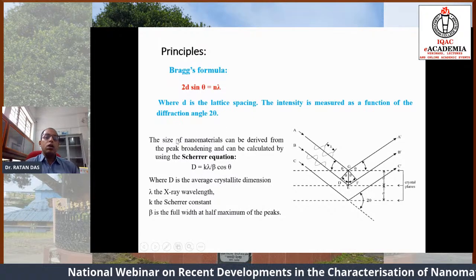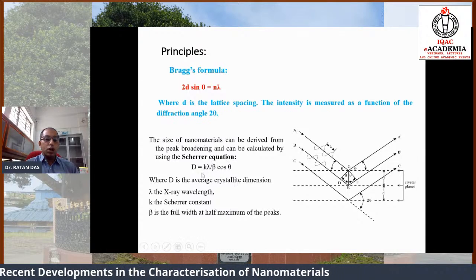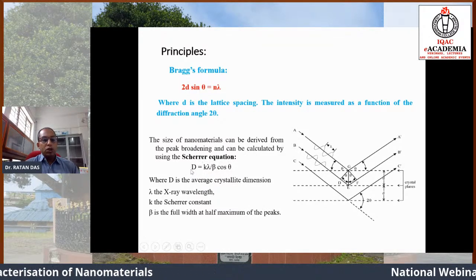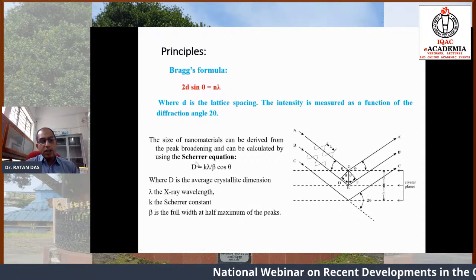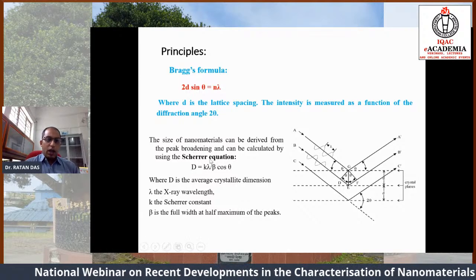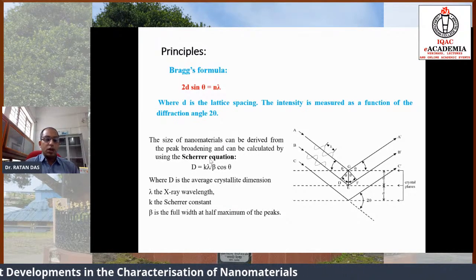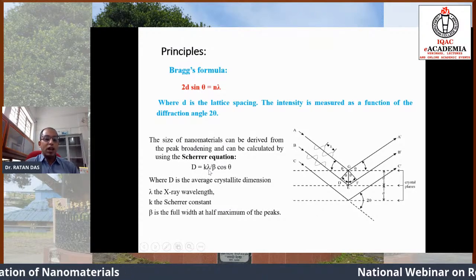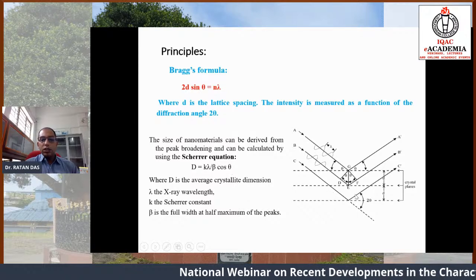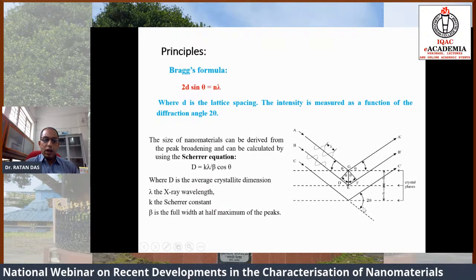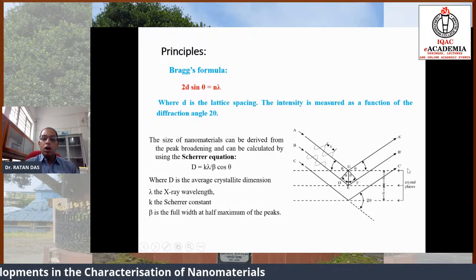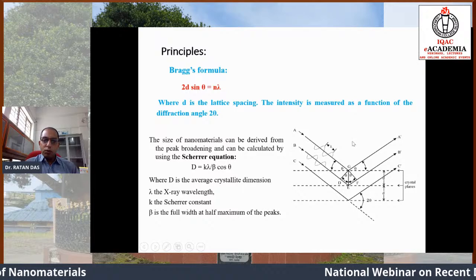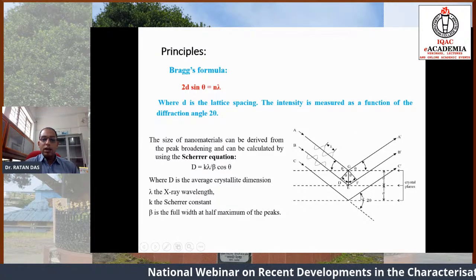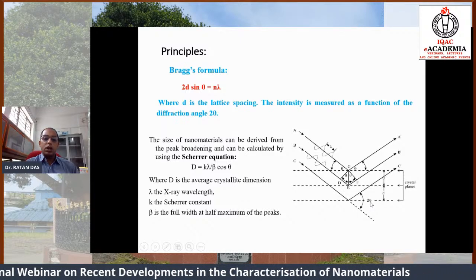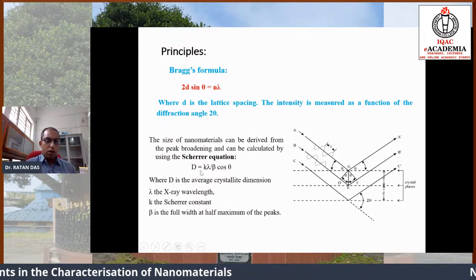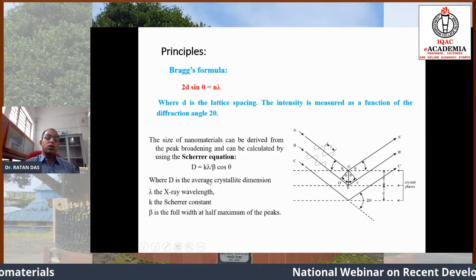Now, in that diffraction pattern, one very important formula is what is known as the Scherrer formula. Through this Scherrer formula, we can determine the crystallite size or nanoparticle size. I shall go into the details later, but let me tell you that this Scherrer formula is D = K lambda / (beta cos theta). What is that theta? Theta is half of twice theta. Here the incident ray makes an angle twice theta with the detector, and at the angle of twice theta we obtain the diffraction pattern, and from the twice theta angle we can obtain theta, and we place the value of theta here in radians. D is the average crystallite size or size of the nanocrystals.